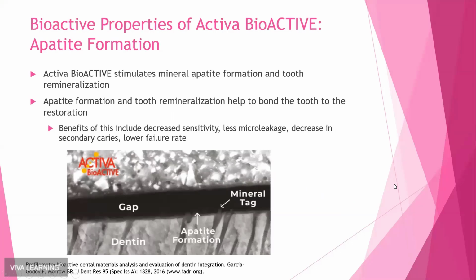So when evaluating the apatite formation, this study was done using scanning electron microscope evaluation and also energy dispersive X-ray spectroscopy. Say that 5 times fast. So when looking at the results of this, what you're seeing on this photo is the top layer is Activa bioactive restorative material, this layer here, and then this is the dentin of the tooth. And you can see the mineral tags that are forming where the apatite or the dentin is bonding to the restorative material. This gap was created when the sample was fractured so that the analysis could be done, but the gap wouldn't typically be there.